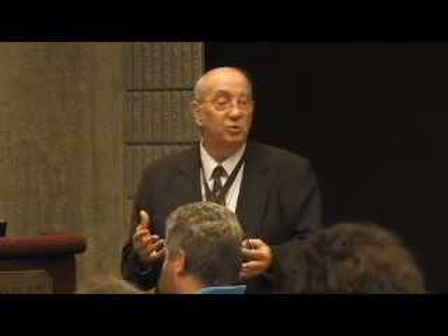This reminds me of one other thing, a pet peeve I have about one of the differences between atmosphere and vacuum carburizing. A lot of times in atmosphere carburizing, and I'm not criticizing this, I'm just making an observation, we don't wait till the load is fully up to temperature and fully soaked at temperature before we start our additions gases. We quote unquote save that extra time, but what we really find ourselves doing is having specifications of a carburized case of 40 to 60 or something like this. Huge variations throughout the load in case uniformity. I'm on a personal mission to change that.